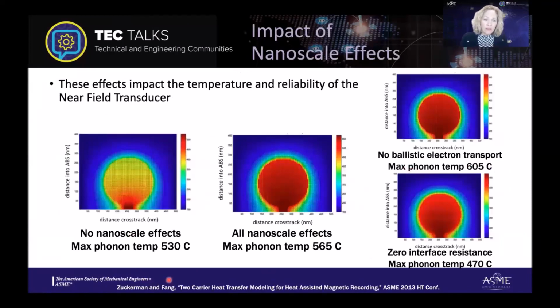So if we look at the device and aren't considering any nanoscale effects, at least in this situation, we're predicting a phonon or lattice temperature of about 530 C. And that's the temperature that's going to determine the reliability of the device. If we consider all of the nanoscale effects, the phonon temperature ends up higher at about 565 degrees C. And so that can be a material difference in bringing down temperature-driven failure modes or being able to accurately predict them. Just to kind of see the magnitude of the individual effects themselves, some of it is that the ballistic transport is offsetting some of the interface resistance, but that's not going to always be the case, and we need to be looking at the relative magnitude of both of those effects.